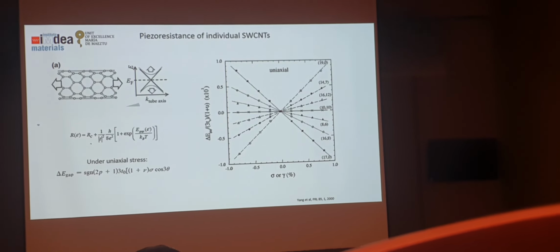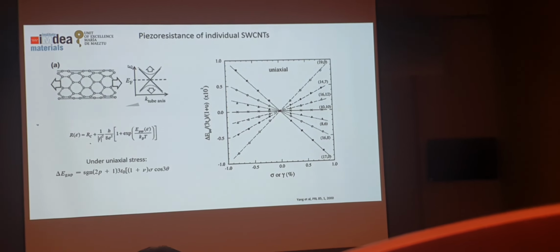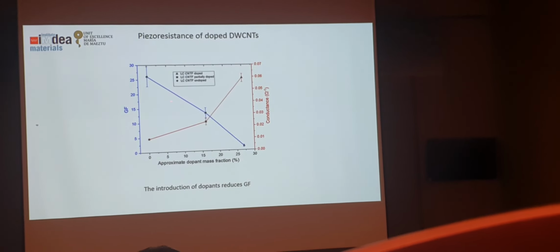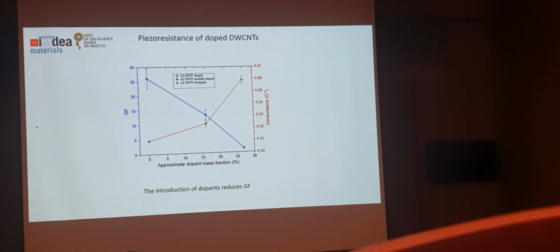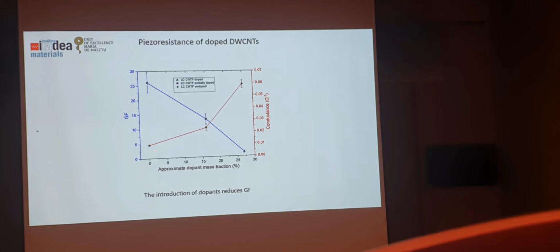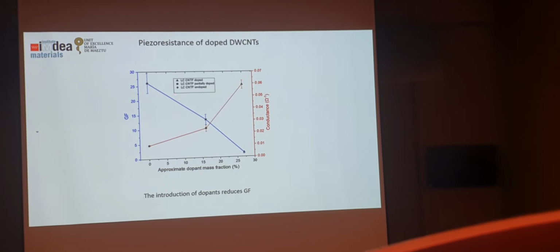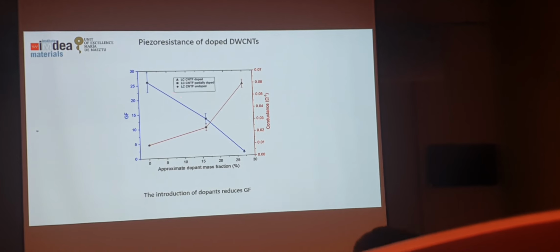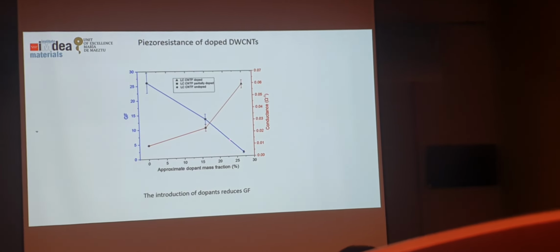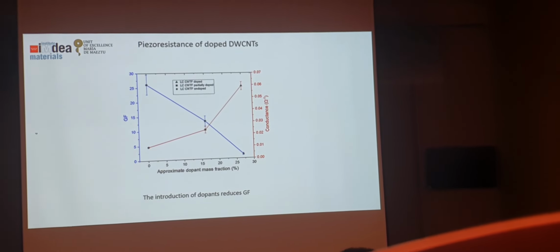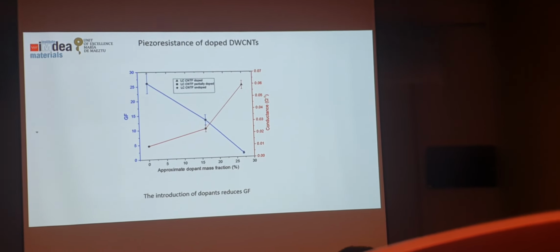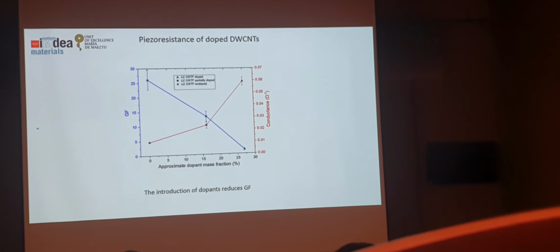And we thought there was probably something else going on. So we tried a few more experiments. This is one. We took some DWCNT fibers and varied the amount of dopant inside, and you find that if they have no dopant, if the dopant is more or less zero, the gauge factor is really very high, the highest we've tested for any fibers. But as soon as you start doping them, that actually drops linearly. So doping them is decreasing the piezoresistive factor. And at first it wasn't obvious to us why.